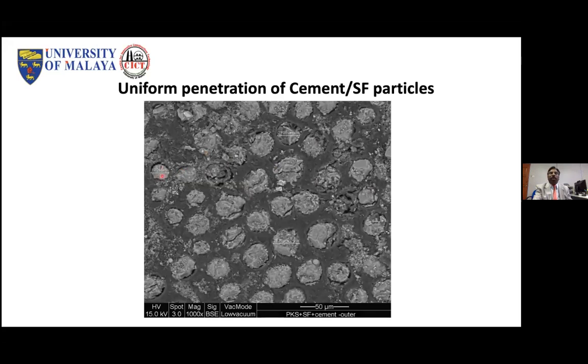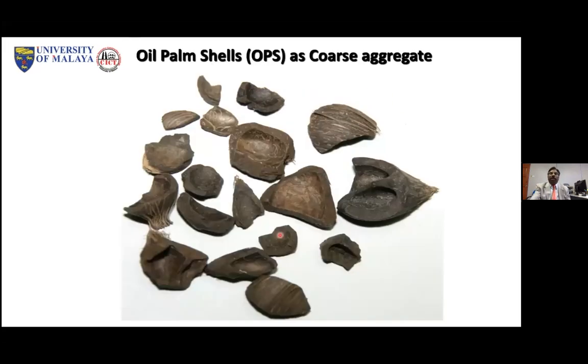See that this is 18.25 micrometer, this is 23 micrometer, this is 27 micrometer. These pores are filled with silica fume particles, very tiny particles. Silica fume is 100 times finer than cement particle. So what happens here? They are so fine that they can fill, and improve the bond between this convex and this concave surface and the mortar. Mortar means the cement and the cementitious particle with the sand, they bind together.